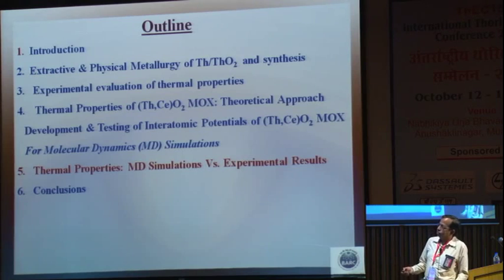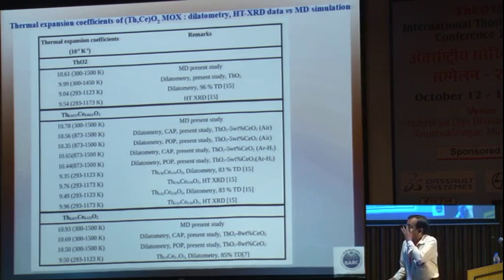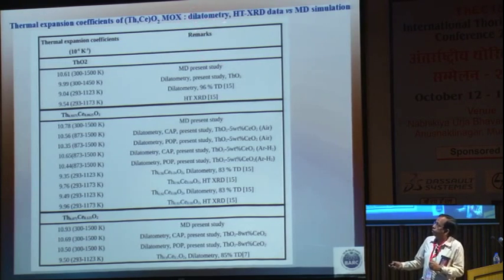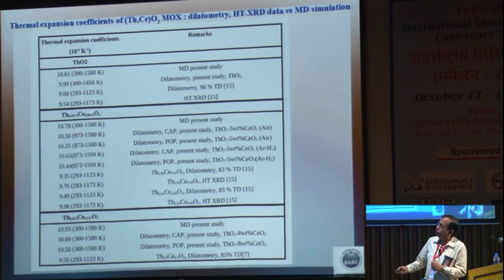So, in the final section I compare the results obtained by MD simulation and experimentation for these alloys, and that is shown both in tabular form and graphic form. Here we have the thermal expansion as evaluated by dilatometry and high temperature XRD, and the MD simulation for these thermal expansion coefficients. The MD simulation results are for ThO2 and also for all the other mixed oxides. They have been compared with the experimental results, and you can see the variation between these, for instance, this is MD and this is dilatometry, this is theory, this is experimentation. There is reasonably good agreement between these two.